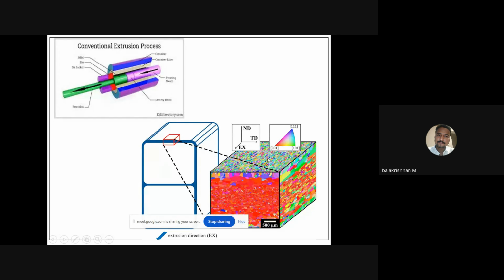The grain formation is very fine in the top area. In the middle it is totally different. On the side also, the 001 plane is perfect, but the 111 plane is not perfect. Similarly for 101. Here we can observe that the enhancement happened on the surface itself.